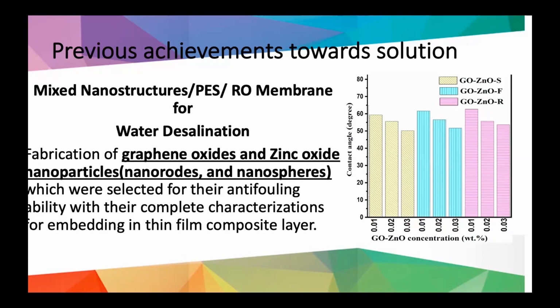What is meant by the traditional way? These nanoparticles were embedded not in the membrane matrix, but in the thin film composite, which is still a very sensitive layer. Sensitive, I mean, it loses its activity after prolonged chemical treatments. So this study was about how to modify the thin film composite layer. These nanostructures were added to the aqueous layer for the thin film composite.